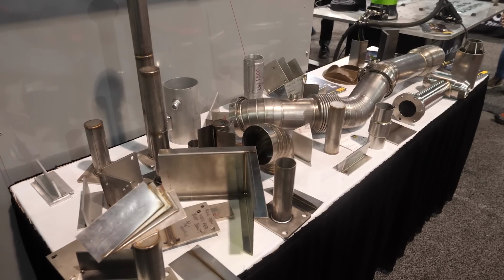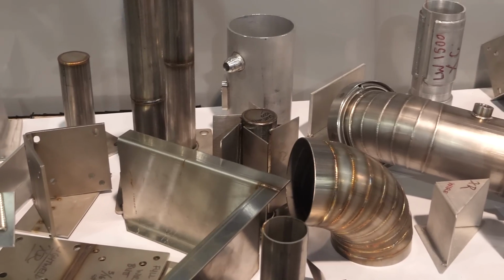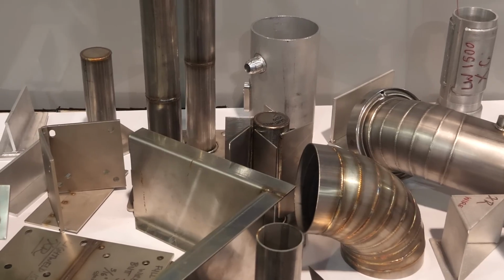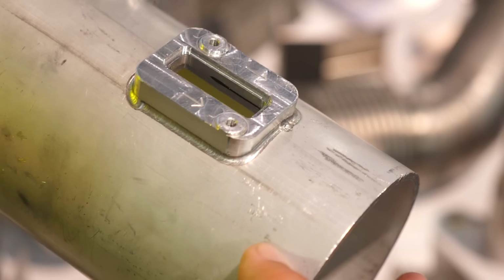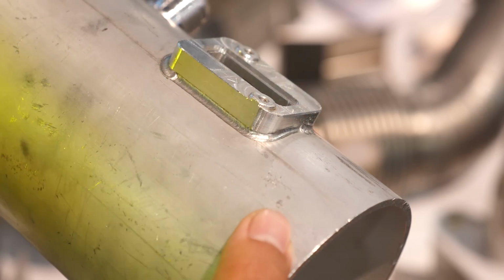Some of the demonstration pieces that you're welding there are relatively thin pieces of stainless, and the impressive part there is just witnessing how little distortion there is of the material once it's been welded. But on the flip side of this, how thick can we work with these machines? So depending on the model, we can get full penetration up to 1/4 of an inch. It's not limited to the material thickness, but you can get 1/4 of an inch penetration into the material.